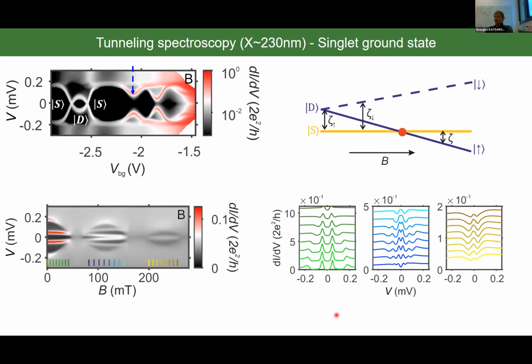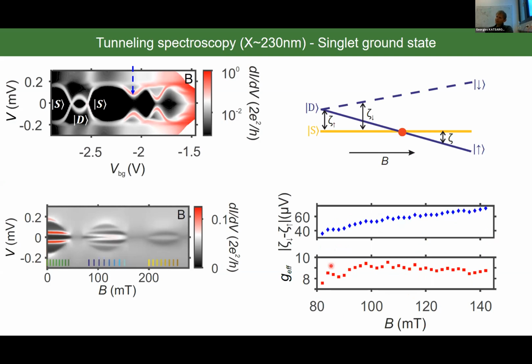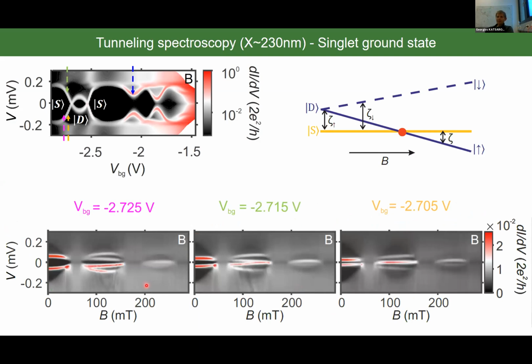Before I move on, let me just tell you that from the splitting of zeta up and zeta down, we can extract the g factor. And we extract again a g factor of 10, which makes sense because it's the same device. So now, depending on the backgate voltage, we can tune the position of our zero bias peak. If we change our gate voltage in this range, you can see that either you don't get any zero bias peak within the first 2 lobes, or if you go to the yellow position, you can actually tune your zero bias peak to be at the first lobe.